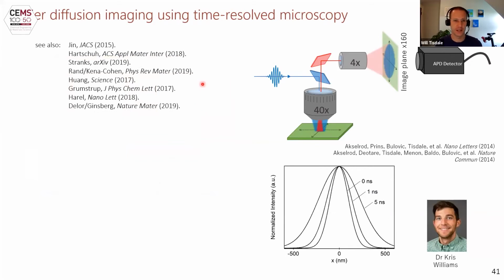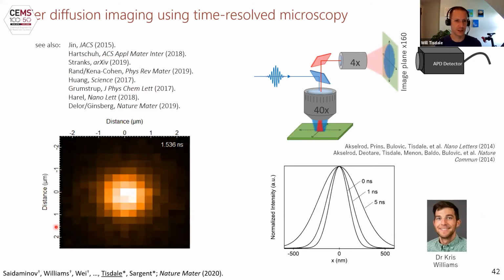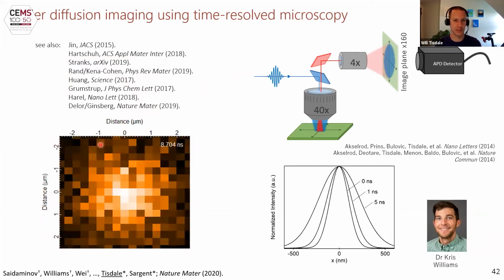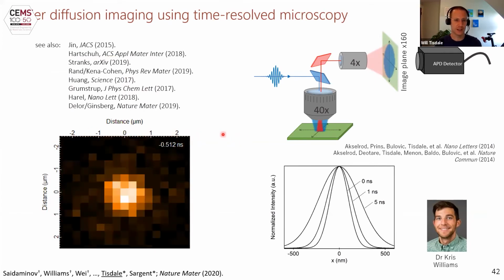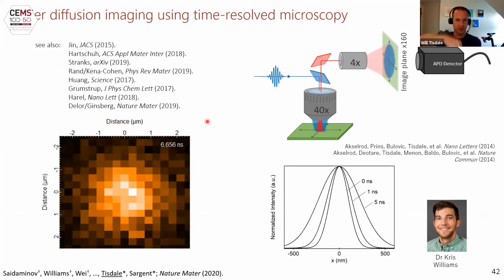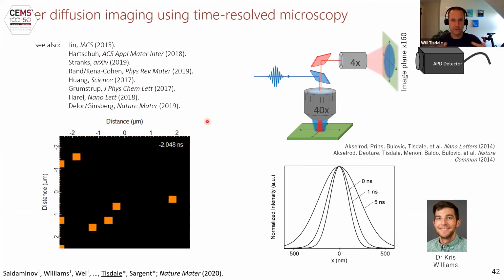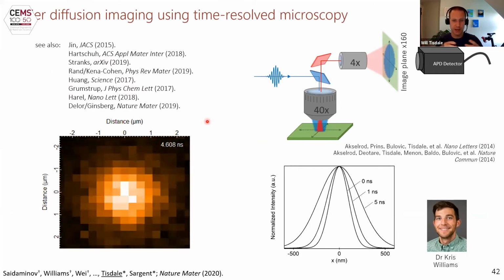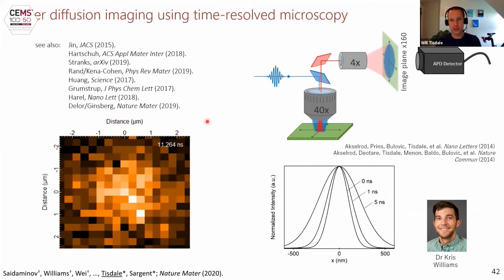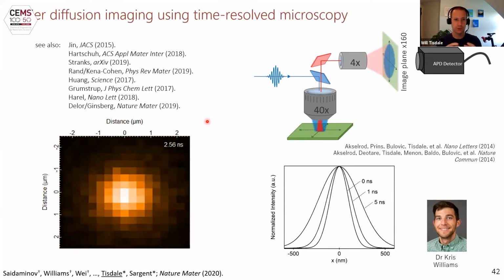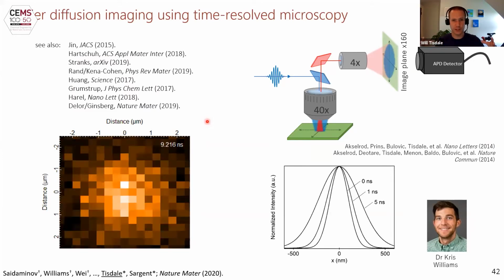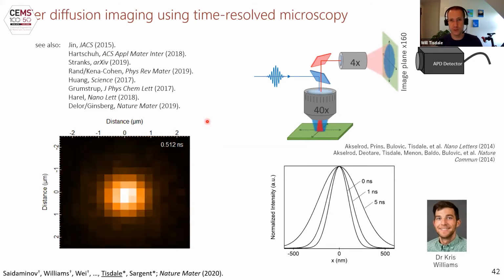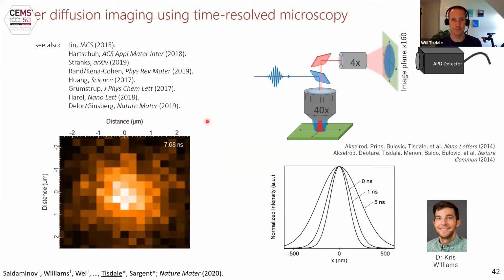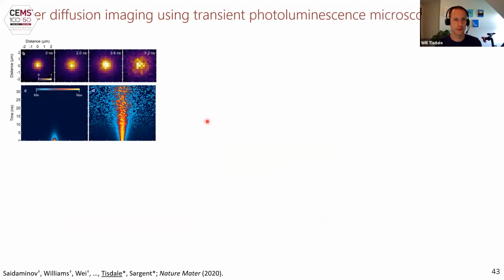Many groups have been doing this over the past few years, but this is the type of data that we collect. So this is a two-dimensional map. This is one spatial dimension in the surface plane and another spatial dimension. The idea is you take a tightly focused laser pulse to excite a distribution of charge carriers. They diffuse outward from areas of higher density to areas of lower density, and then recombine and photoluminesce. And if you can visualize with enough time and spatial precision the spreading of that distribution, you can directly measure the diffusivity of your charge carrier population in time. So these are some snapshots, just like I showed you. At early time, you have a narrow spatial distribution. As time goes on, it broadens out.